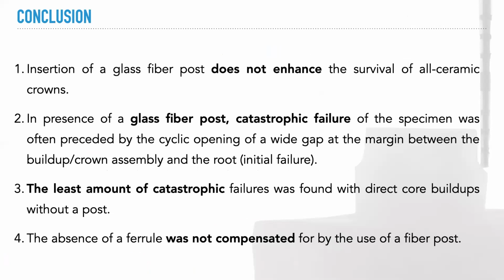In the presence of a glass fiber post, catastrophic failure of the specimens was often preceded by a cyclic opening of a wide gap between the crown and the root. And the least amount of catastrophic failures was found with direct core buildups without post. And the absence of a ferrule was not compensated by the use of a glass fiber post.